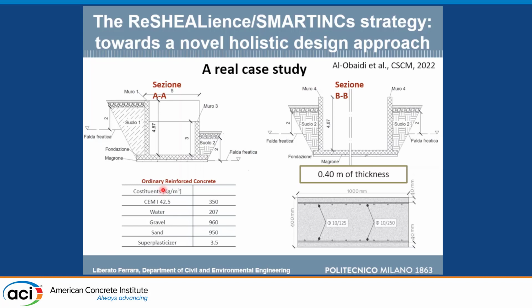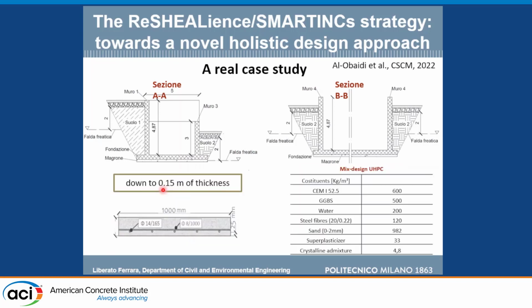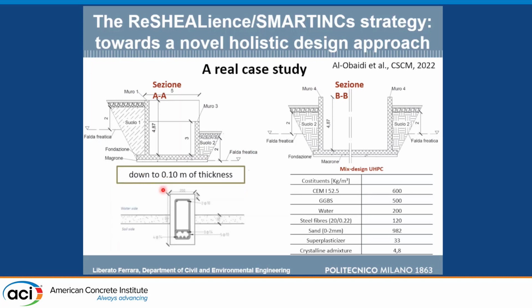So the original reinforced concrete design solution has a wall which is 400 millimeter thick with very deep cover, because the reinforcement has to be protected from the attack of the water, which contains chlorides and sulfates. When we ended up with designing with UHPC, we used in this case a hybrid structure. The height of the wall, 5 meter, did not allow us only to use fiber reinforcement. We scale it down to 15 centimeter thickness, or if you design slabs and buttresses, the thickness can go down